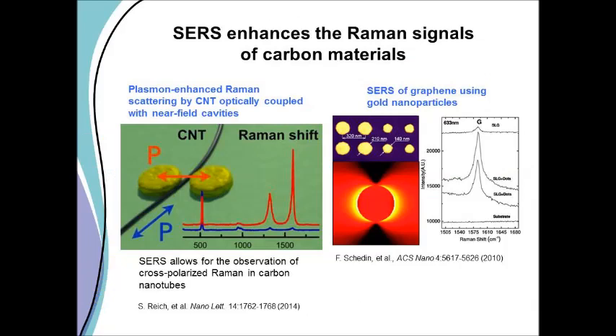That such an effect exists, Stephanie Reich gave a talk earlier this year that I heard that was very beautiful. What she did, she put a carbon nanotube between two tiny gold particles and got a huge enhancement factor. It gives you an idea. And in the UK, I guess it's in Manchester, Schedin, he must be in Manchester. This is Manchester work, maybe he's in Cambridge, but connected with the early work in graphene. And so they did an experiment on SERS. They got a big enhancement factor shown here as well in graphene. So graphene shows SERS.